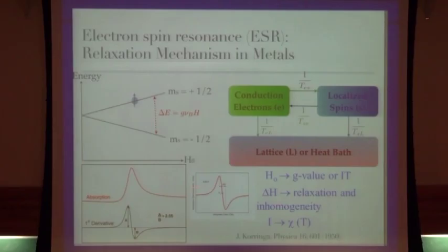And the intensity of this line is proportional to the susceptibility, right? So if you have a Curie, a localized spin, the intensity should grow in a Curie-like manner. If you have a conduction electron resonance, it should be constant, so it should follow the susceptibility. Also, the line shape gives you some information, because the line shape is affected by the skin depth of the microwave and also by the diffusion of the electrons if you have a metal. So in a metal, we usually have an asymmetric line like this one, which we call Dysonian. When you go to an insulator, you have a symmetric line that we call Lorentzian. So this height here is equal to this in a Lorentzian, and the height A is larger than B in a Dysonian.